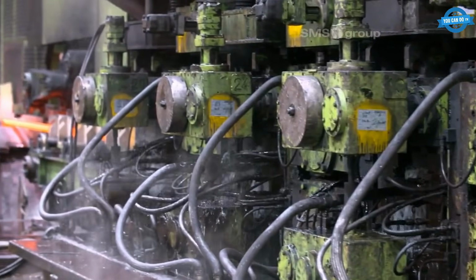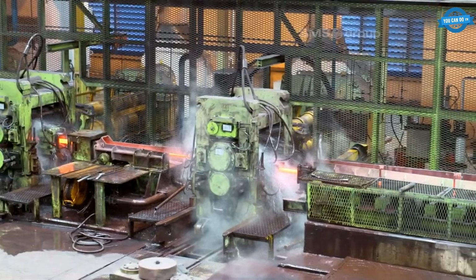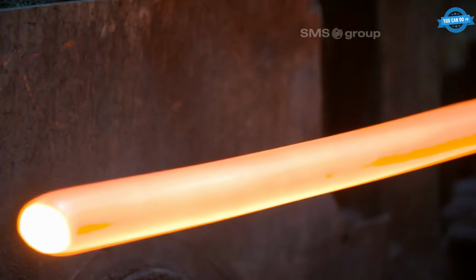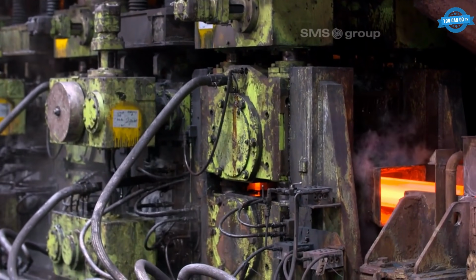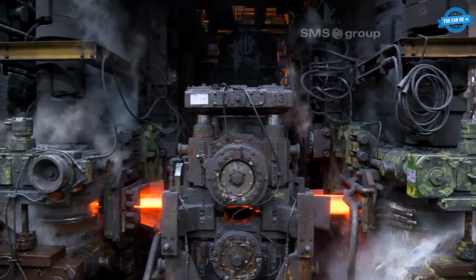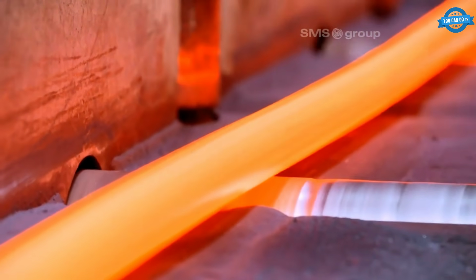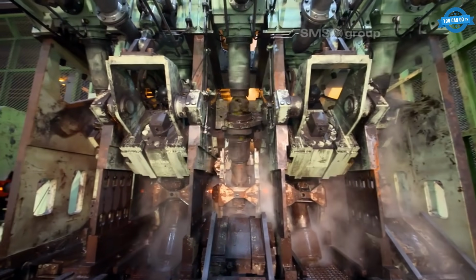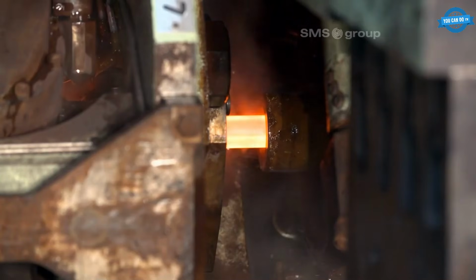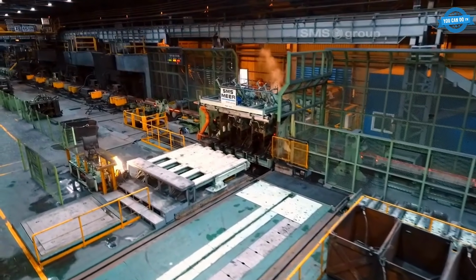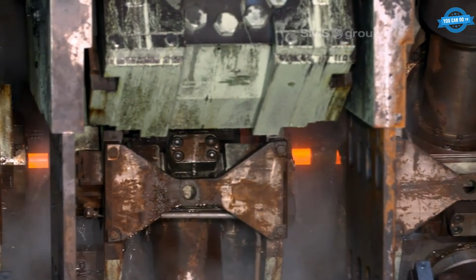Now the shaping begins. Slabs and billets get reheated to rolling temperature, then squeezed between huge rollers that stretch them into thinner, longer shapes. A modern bar mill can produce hot-rolled coils, rebar, structural beams, wire rod, and precision bars all from the same input, just by changing rollers and pass schedules.